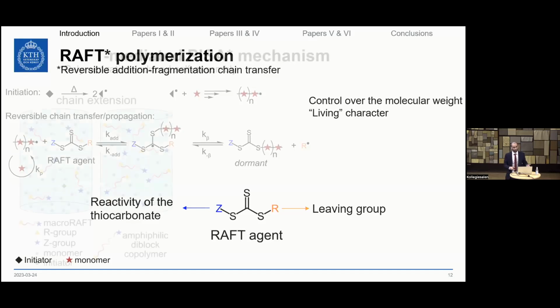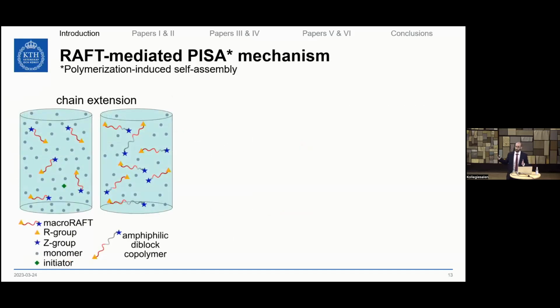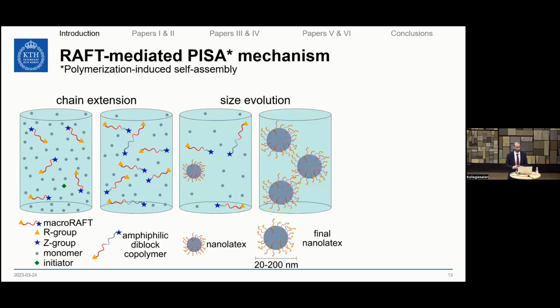In this thesis, we have combined RAFT polymerization with a technique that is called polymerization-induced self-assembly, or PISA. It is a two-step process, where in the first step, we polymerize a hydrophilic monomer in water in order to create a hydrophilic macro-RAFT agent, which in the second stage, we chain extend in water with a hydrophobic monomer. This will create an amphiphilic diblock copolymer, which above a critical ratio between the hydrophilic and the hydrophobic blocks, will self-assemble into nanolatexes, which will evolve in size until the end of the polymerization.